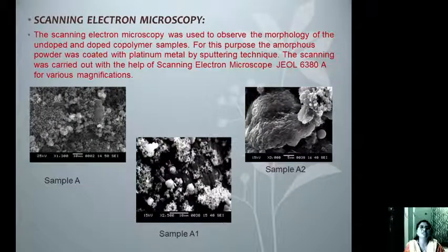when the sample was subjected to scanning electron microscopy, we observed that the self-doped sample shows a diffused matrix-like structure in which small globules have been observed. These globules are totally distorted due to the undoping process. So for the undoped sample, we can see that there is a base-like material and the globules have been reduced. But when the same sample was doped with NiCl2, we observed a flake-like structure, with big chunks and few globules. So the morphological changes are clearly visible.